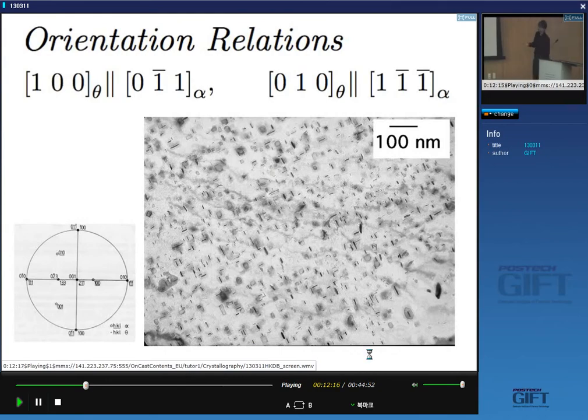We've already looked at some orientation relationships between the gamma and the gamma prime, where I explained that the cube edges are parallel. So 100 of gamma is exactly parallel to 100 of gamma prime, and that's why we regarded the turbine blade as a single crystal, even though it contained about 70% of precipitates.